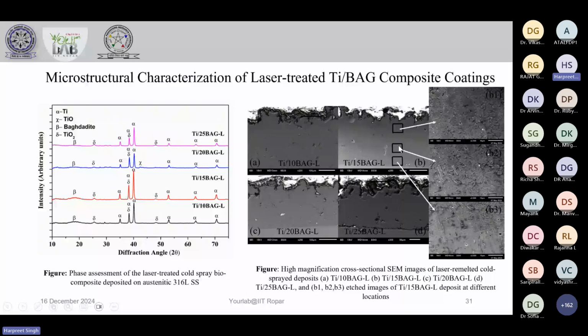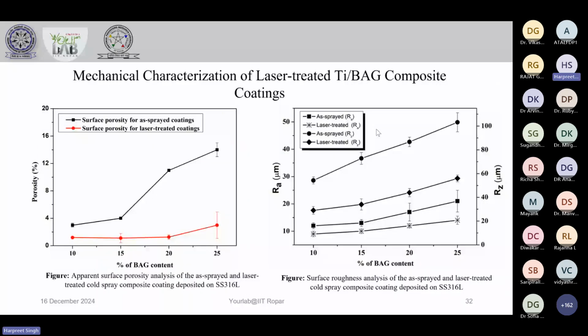Another advantage is that the laser treatment helps you, as I told you, to control the depth of the heat treatment. But when we do the overall heating, the conventional heat treatment of your samples, the problem is that there is a diffusion between this coating and the substrate, right? Which can be nicely avoided by controlled laser treatment, which he demonstrated, and of course he got some other benefits in terms of grain refinement and all that. And then he tested these coatings under several environments. I think let me stop here